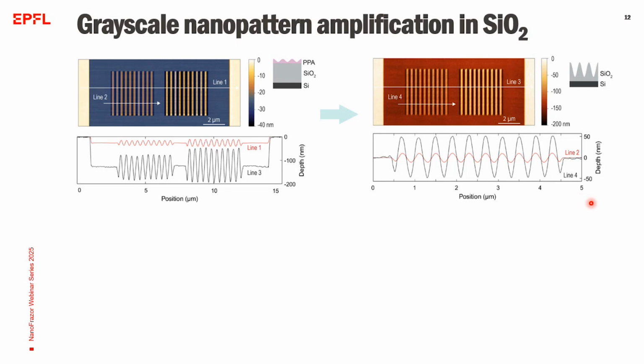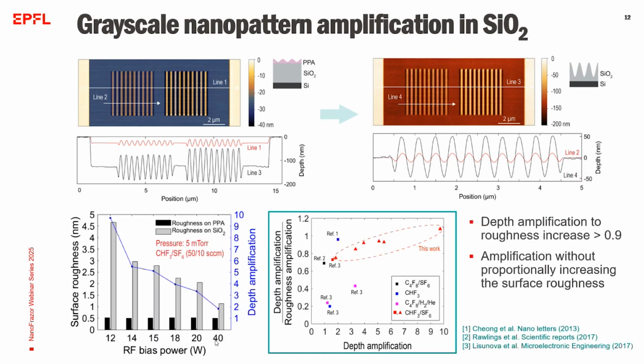And as we observe in this comparison, we achieve amplification without any shape distortion, and there is no additional surface roughness introduced during the plasma etching process. So with our optimized etch process, we succeed in keeping the depth amplification to roughness increase ratio close to 1, mostly over 0.9. And this means that the transfer is achieved without proportionally increasing the surface roughness. So finally, we can conclude that we amplify only the depths vertically, but we don't introduce any extra roughness from the plasma process itself.